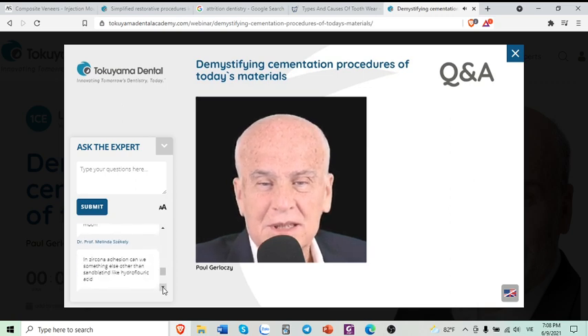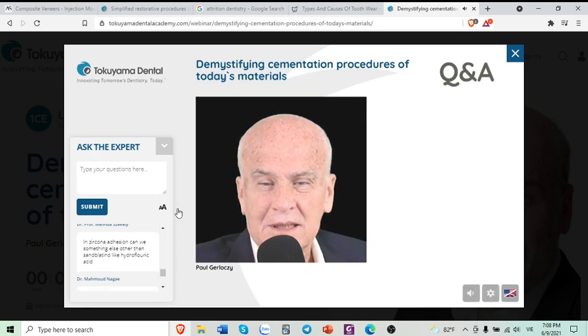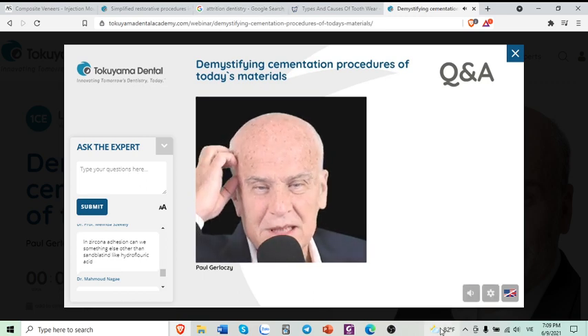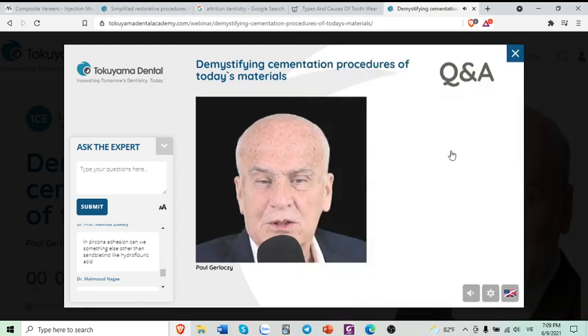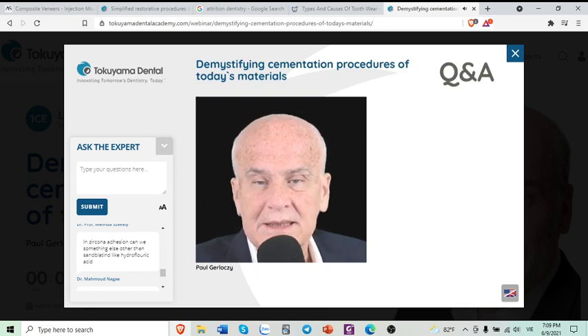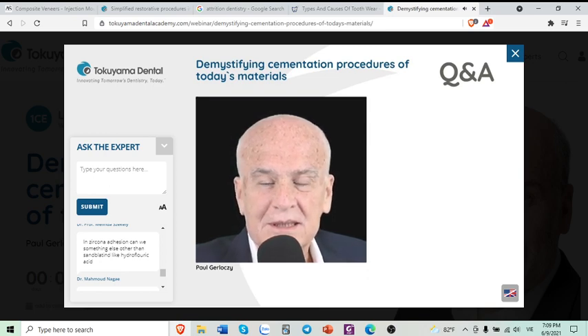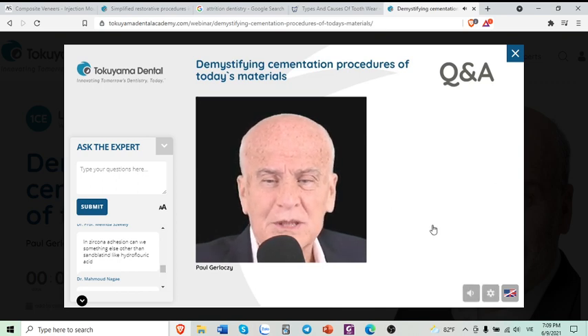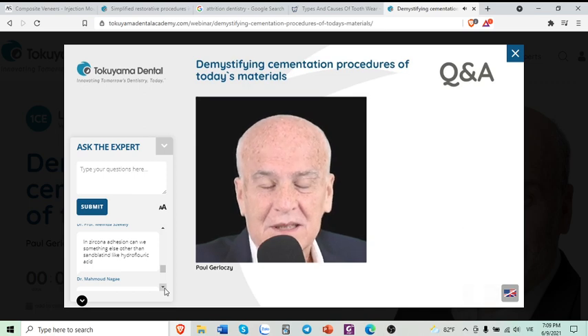In zirconia adhesion, can we use something else other than sandblast, like hydrofluoric acid? No, if I understand this right, if you don't use hydrofluoric acid for zirconia, we cannot etch zirconia at this time. Remember from the lecture, the slide with the blue and the yellow. I don't know if that sticks in your mind. All the materials that have the blue, which is the glass phase, those can be etched. But zirconia doesn't have a glass phase, so it cannot be etched, at least not with hydrofluoric acid. They're working on that.